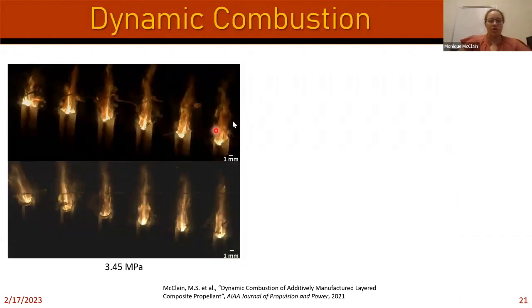So here are just some stills showing the exact same phenomenon for those propellants. But we really wanted to understand, again, how does the surface evolve over time? How does this middle burning layer of propellant compare to the burning rate of the same thing, but just not layered? So for example, does this iron oxide layer burn as fast as just a normal iron oxide propellant, like a single material propellant? And same for the nano aluminum.